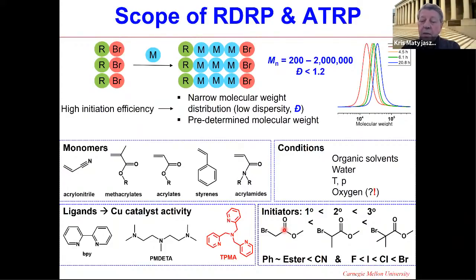Initiators very often mimic the structure of the growing species, and tertiary structures like isobutyrates are more active than secondary propionates or primary acetates. Radical stabilizing groups: cyano would be better, and phenyl and esters are pretty similar. The choice of halogen depends on the stability, or bond dissociation energy, between not only carbon and halogen, but also copper and halogen. Therefore, bromides are more active than chlorides and more active than iodides, which are normally much weaker bound to carbon atoms.